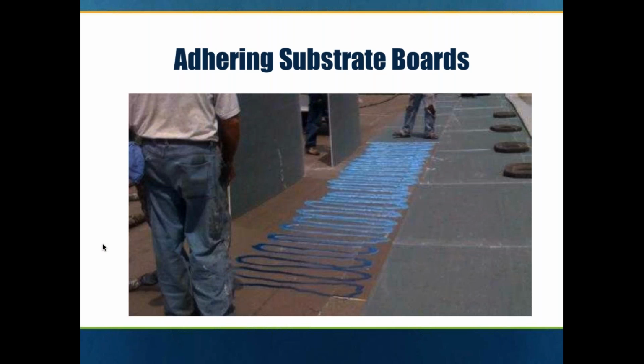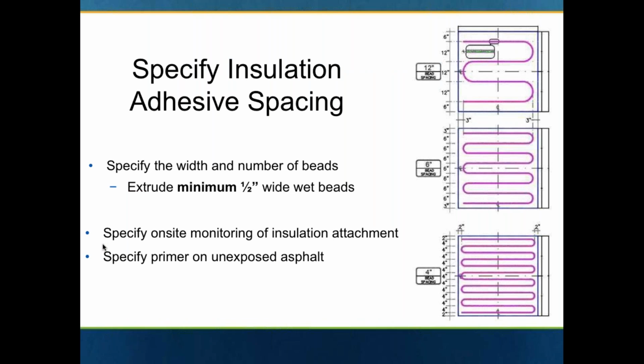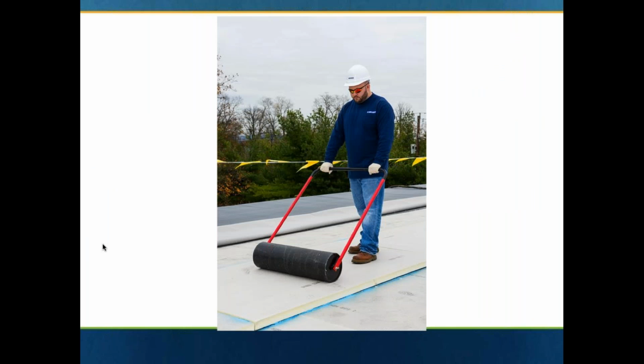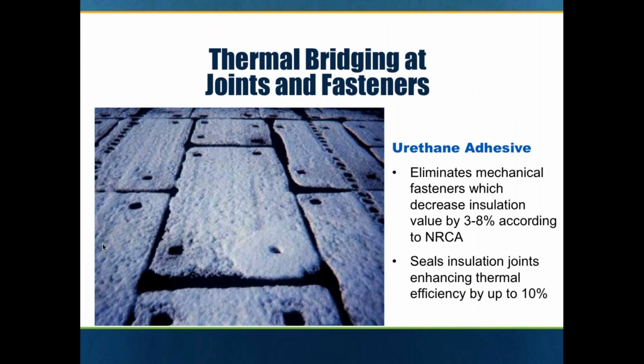You can also install the adhesive in ribbons. And in this application, this is a cover board being installed over insulation. And there are specific patterns for ribbon spacing based on the uplift pressures you're trying to achieve. So there are different ribbon spacings for the field, perimeter, and corner of the roof. As mentioned, a 150-pound weighted roller would be rolled over the insulation to fully embed that into the adhesive. And what this does by using the urethane adhesive and staggering the joints of the insulation is it eliminates the thermal bridging at those joints and the fasteners. And so it's a much more energy efficient system than typical steel screws and plates.